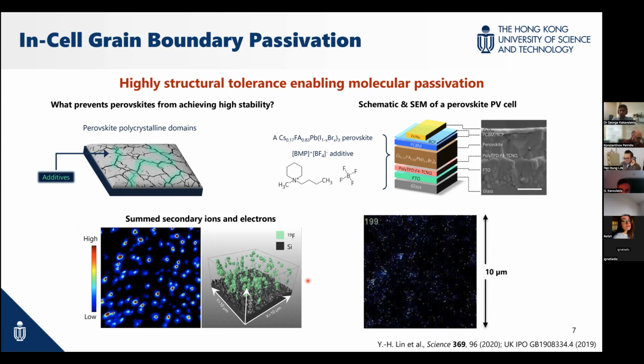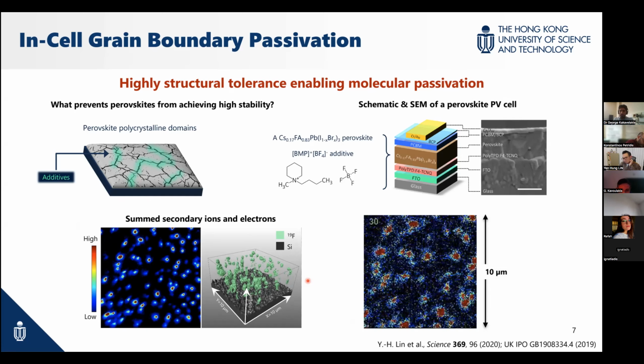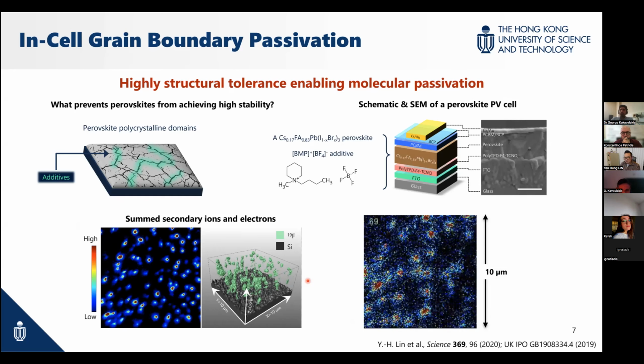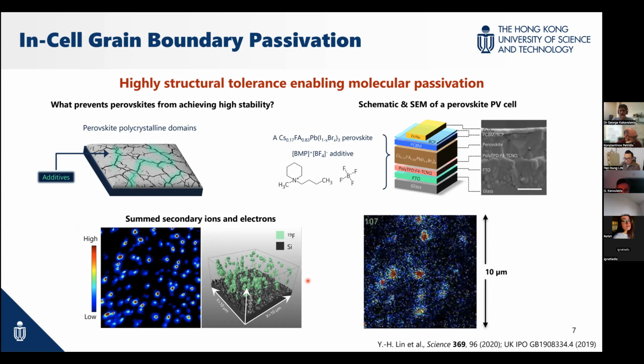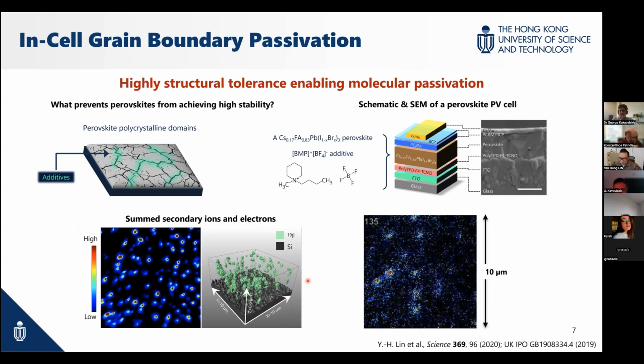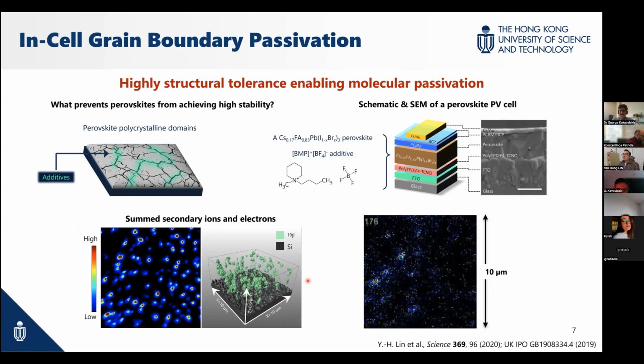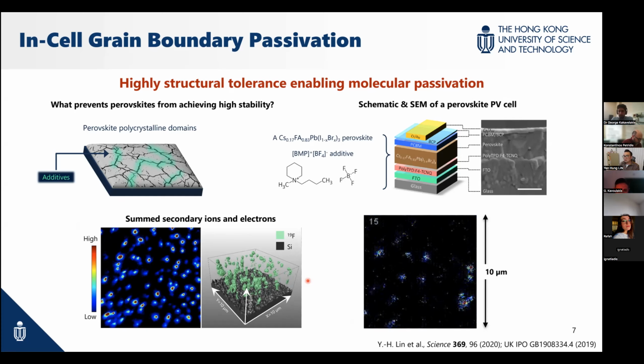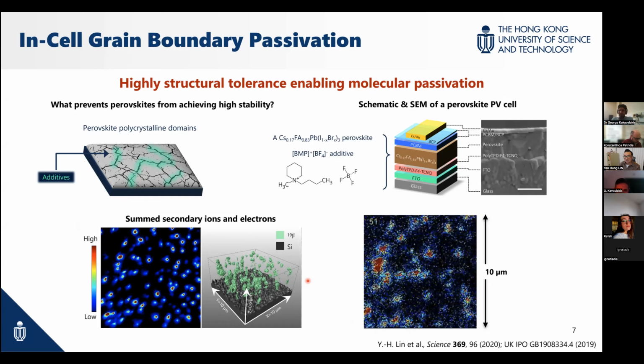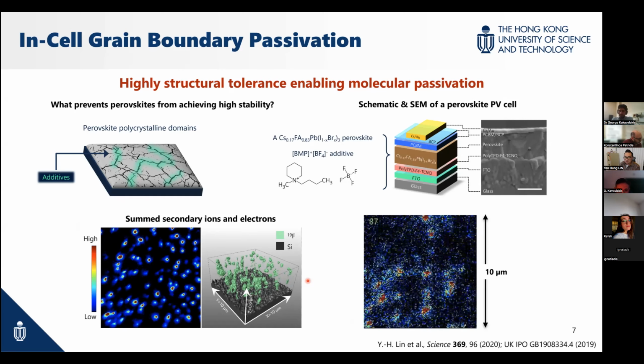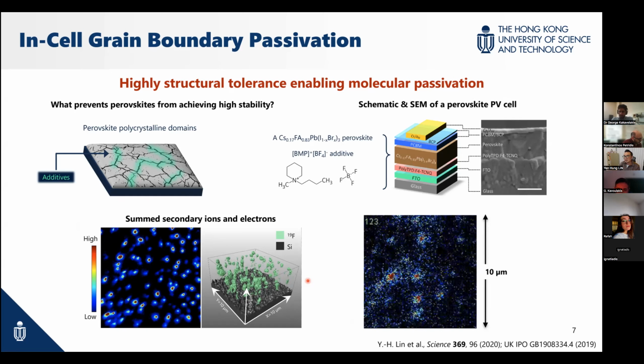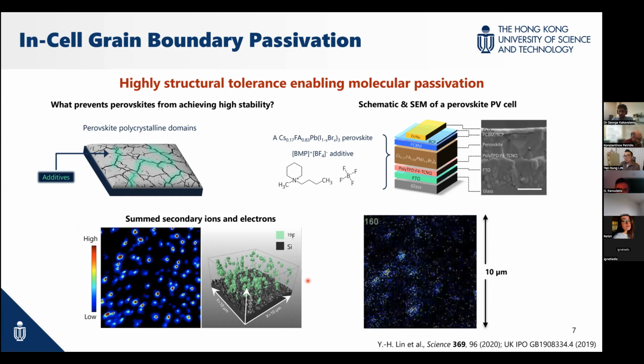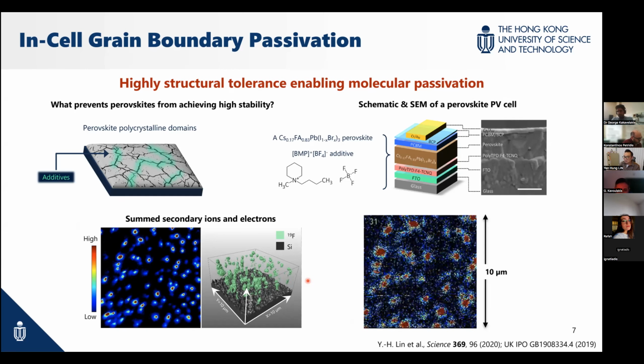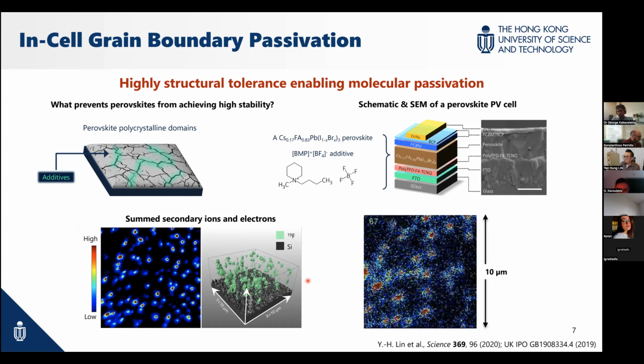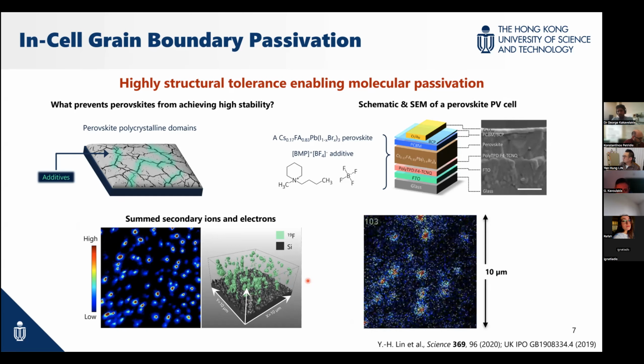So I don't know if I cover everything here. And George, I would also like to mention one thing. For this kind of FAPbI3 work, especially published last year, there are so many impressive results, 25 or 26%, especially for inverted cells. But one thing I do notice is that when they do a stability test, a lot of times they switch to slightly different architectures, and we see a drop, because we did a little bit of statistics. If they did report the performance for their cell for stability tests, it's around 10% difference in terms of efficiency. This is something I'm more puzzled by. I don't know if you noticed that part.